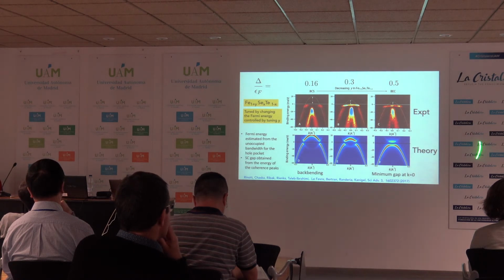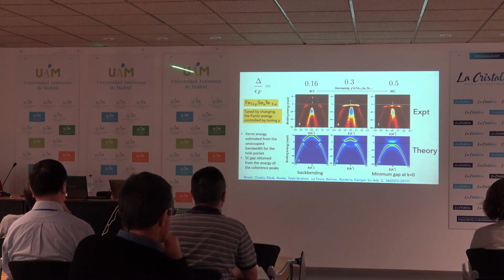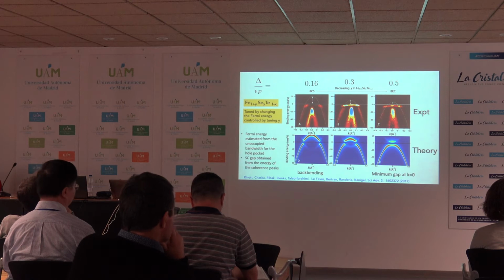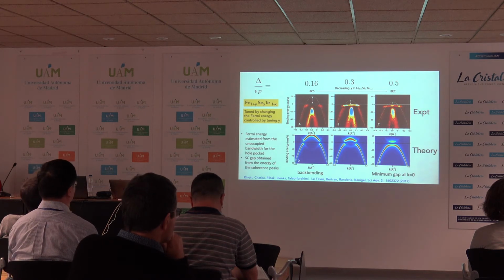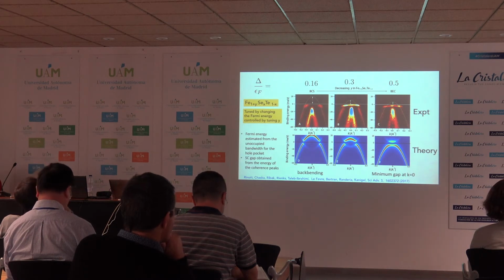Okay, so very recently, there are some very beautiful experiments by Amit Kanigal's group, and Mohit is a co-author on that. It's on iron selenide. In most materials, this has been the problem of how to tune toward a BEC regime, and you can't tune the interactions very much. They are whatever is given in the material. In cold atom experiments, it's possible to tune the attraction using Feshbach resonance. In materials, on the other hand, what is important is to tune this ratio, delta over EF.